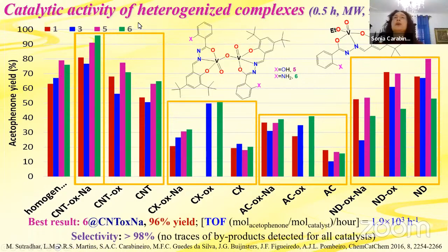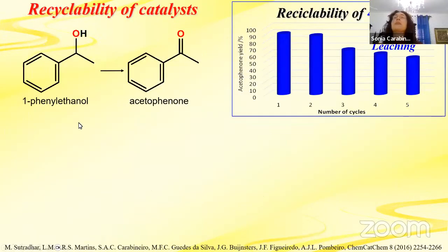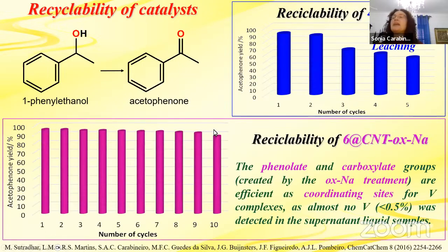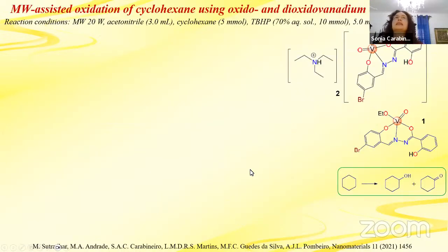Okay, so the best result was complex number 6 here with NH2, here it's this X, and it was 96% yield and very high selectivity as well. For recyclability, on nanodiamonds there is a little bit of leaching, but on carbon nanotubes it is much better. So it seems that the phenolate and carboxylate treatments are very efficient as coordinating sites. They anchor the complexes better. And almost no vanadium was detected on leaching. See, very good up to 10 cycles.